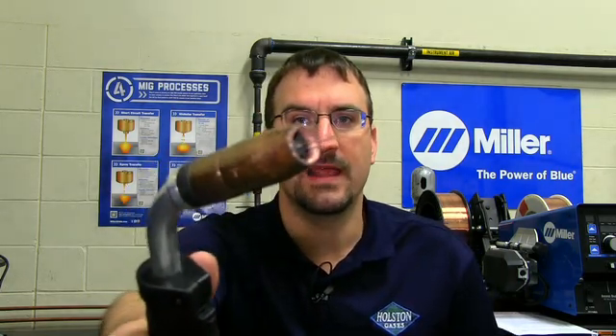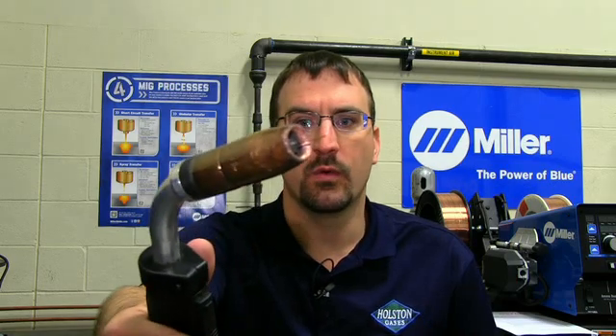Now, the correct way to set up your contact tip and nozzle is to have your contact tip recessed in your nozzle approximately an eighth of an inch. And you can order or set your MIG gun to come this way if you know that the customer is going to be using spray transfer. The reason we do this, there are two reasons. The first reason is because spray transfer is a higher heat input process and we want to protect the contact tip so it has longer life.